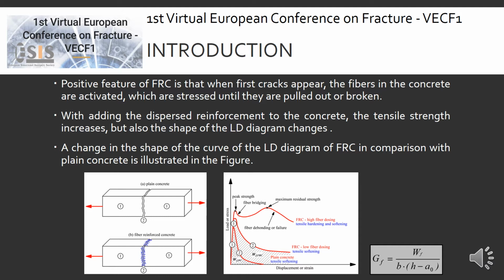A positive feature of fiber reinforced concrete is that when the first crack appears, the fibers in the concrete are activated, and are stressed until they are pulled out or broken, which adds dispersed reinforcement to the concrete. The tensile strength increases, but also the shape of the load displacement diagram changes. A change in the shape of the curve of the load displacement diagram of fiber reinforced concrete in comparison with plain concrete is illustrated in the figure.